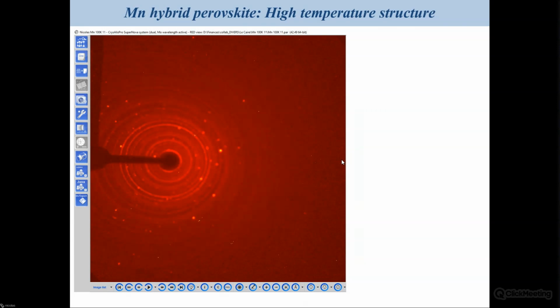So we asked our colleague for powder diffraction to give us a possible unit cell, and this is what he proposed, which is very different to the one we had initially because it has completely different parameters and a different system. But with that, it has been possible to treat the peaks we extracted from the data sets after the first heating, and we obtained such a model, which is of course very surprising because it is completely different to the initial structure, which is plotted there.